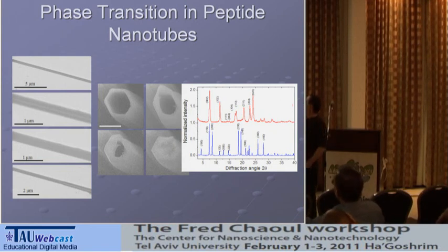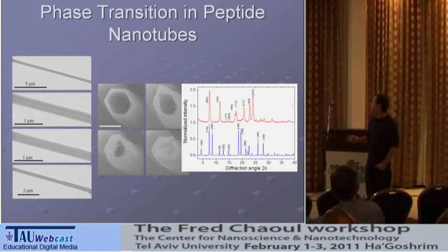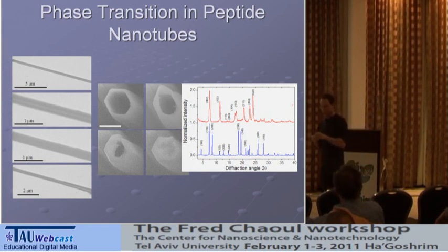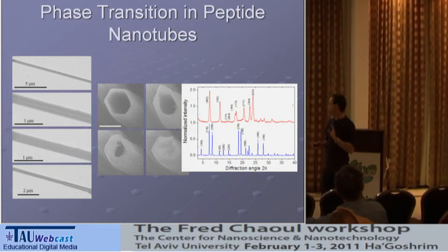This is the peptide nanotubes. You can see a hole in the middle. It's hollow. So we started to heat it with E-beam. This is taken in a STEM. So after a few seconds, this hole is just closing. And you can see when we zoom out, this is the heated area, this is the non-heated area. And we can see here, this is closed tubes, this is open tubes. We can make them stand and follow a little bit the closing of the tubes. And as we heat, the tube is gradually closed. I didn't bring the movie, so don't worry.